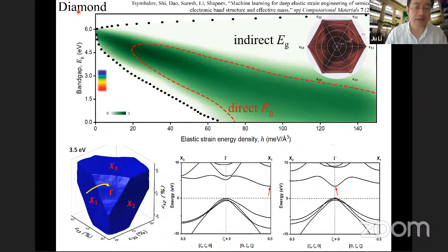density of band gap for diamond, right? So our common diamond is 5.5 electron volt. It turns out that our experiment that Yang Lu showed is somewhere here. Actually, a few years ago, Subra's group showed you can make it metallic, near metallic in here. So you can easily make a direct band gap. And then it can also fall into the visible range. The visible range is here.